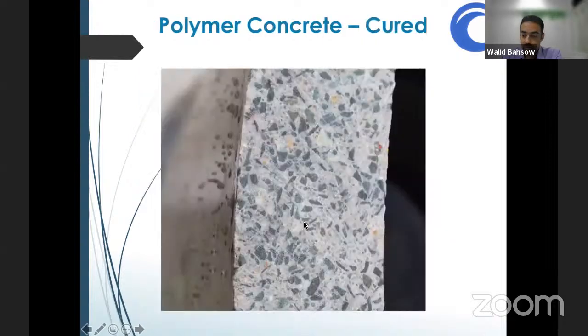The curing process, of course, is much different when compared to concrete or clay pipes. There is no requirement for any type of long-term post-curing or heating. It takes about 1.5 hours to 2 hours max for the polymer concrete to be cured and ready for service. Of course, we recommend waiting about 3 days to obtain the maximum strength. But after 1.5 to 2 hours, the pipes can already be used, or whatever the product is.